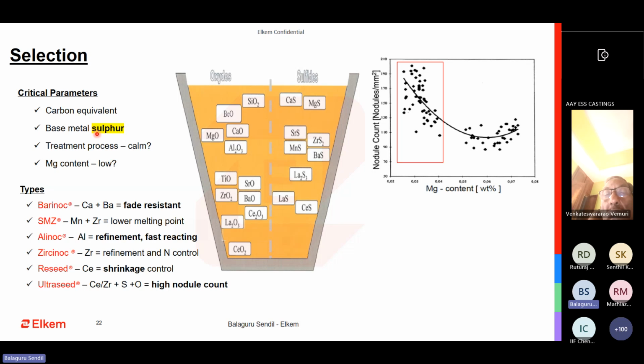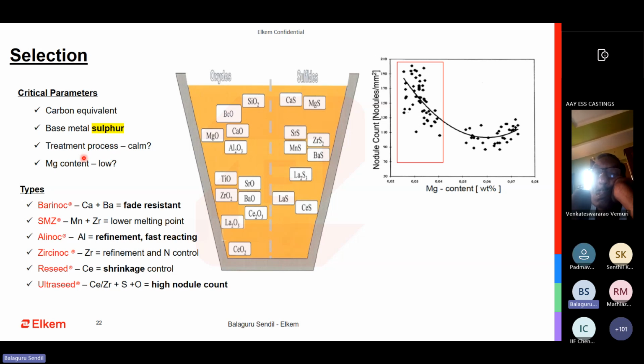Your base sulfur is also very important. If your sulfur is too low, not only do you end up getting a very bad microstructure, your nodule count will also be low. Inoculant directly reflects your nodule count. So if your treatment process is calm, it is better. If residual magnesium content is low, it is better. So this is a correlation between magnesium content versus nodule count. You can see here, this is the ideal range I would like to operate.